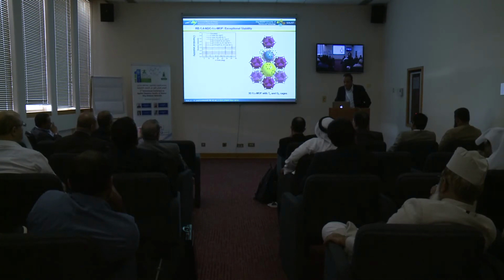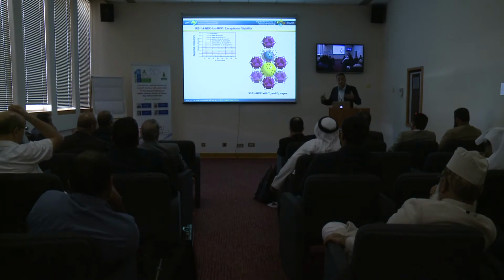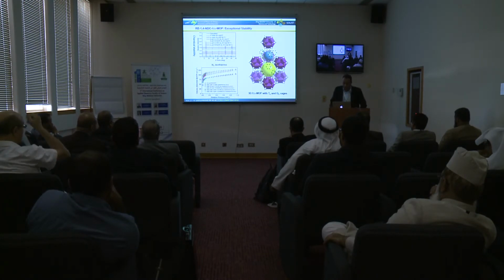So before I get to that, this material is stable, and you can boil it in acid and sodium hydroxide. It turns out that the shorter your linker, the more compact it is. In coordination with the cluster, you enhance the stability. And of course, this is confirmed by the sorption.